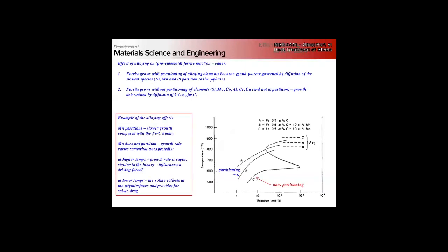So then, remember the austenite stabilizers and the ferrite stabilizers want to partition as the different phases grow. They don't necessarily want to stay uniform. As we grow ferrite, we're partitioning, and that partitioning rate is going to be governed by diffusion.